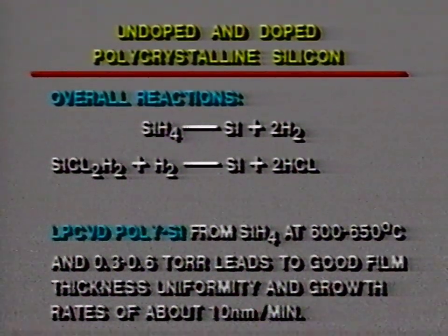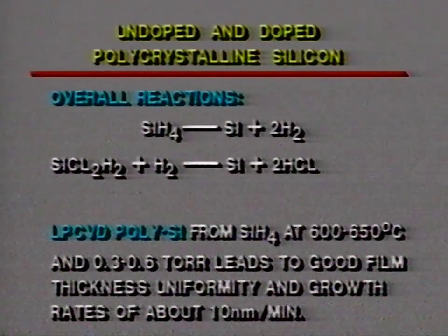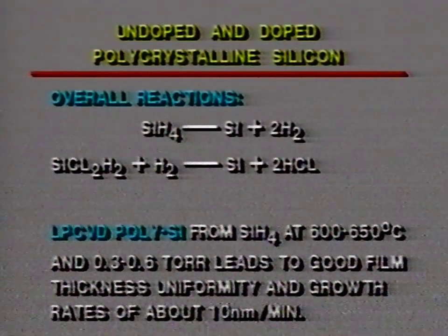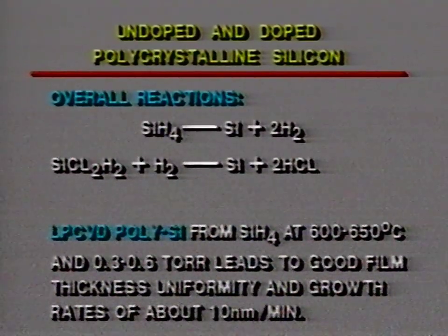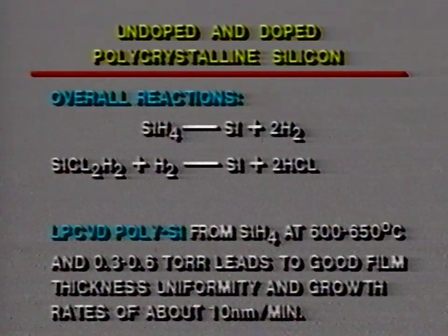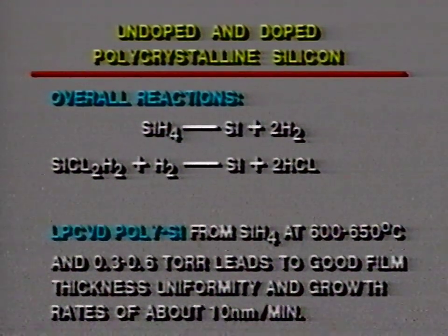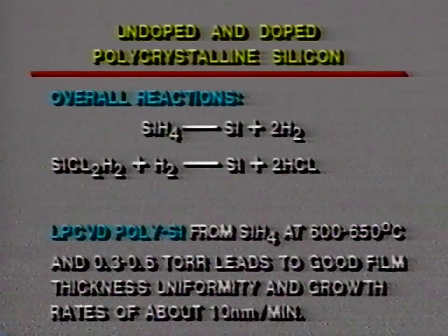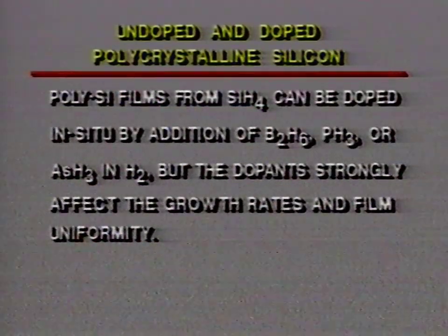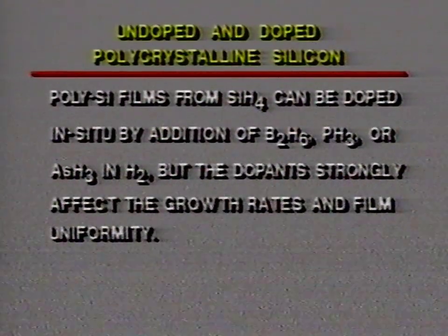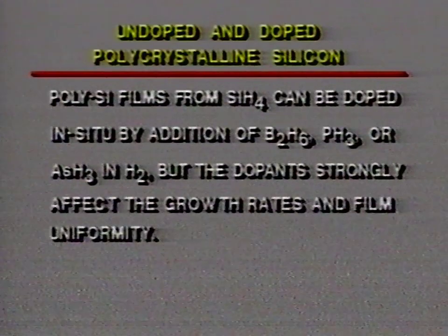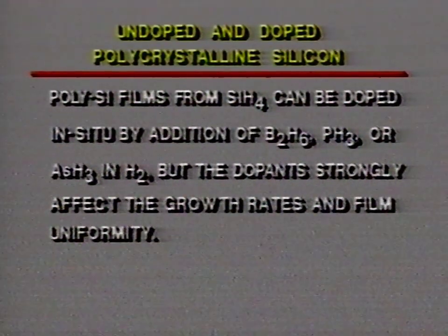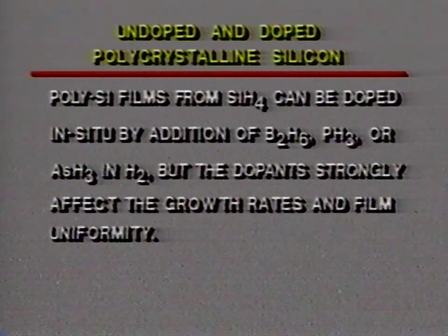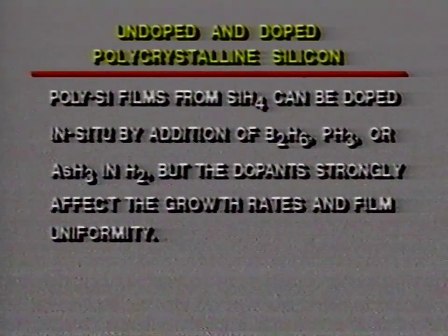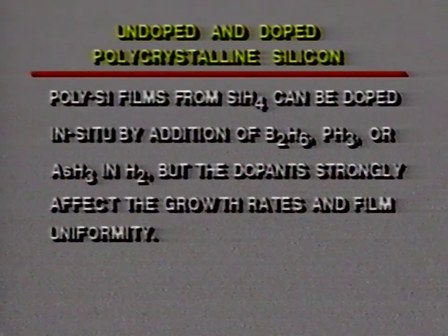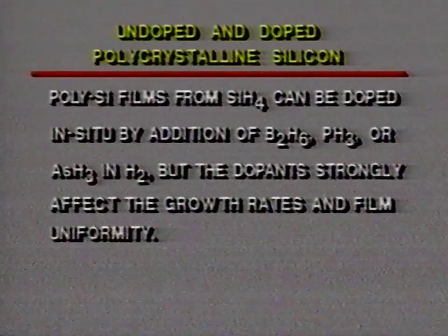Okay, now the LPCVD of polysilicon from silane at 600 to 650 degrees C at 0.3 to 0.6 torr pressure generally leads to a very good film uniformity, that is within 5% variation, and growth rates of approximately 10 nanometers per minute. The polysilicon films from silane can all be doped in situ by the addition of diborane, phosphine or arsine in hydrogen. However, the dopants strongly affect the growth rates and the film uniformity. So we have to be aware of that. And the effect is indicated in some more detail down here.